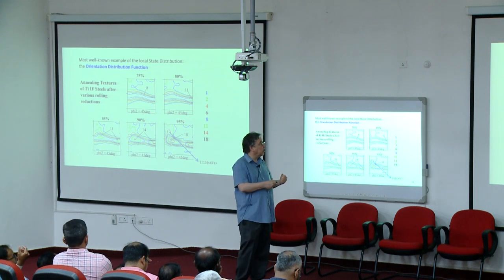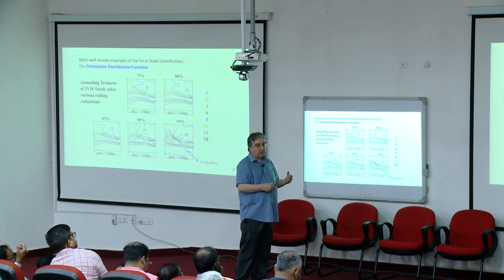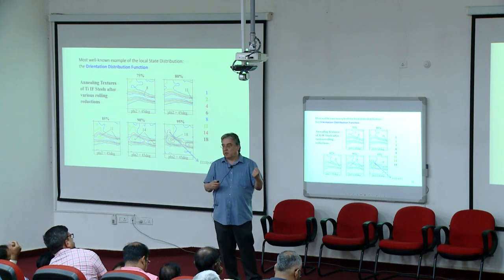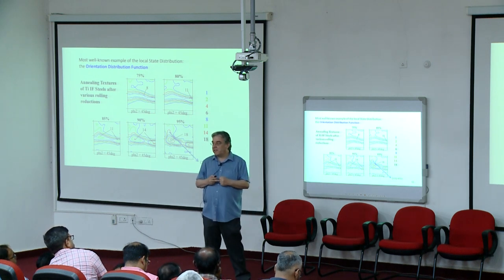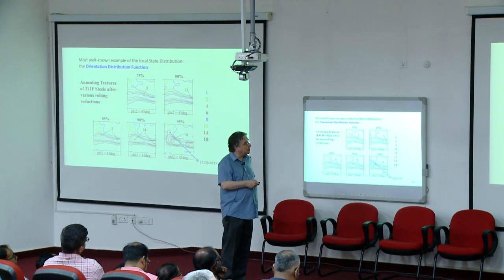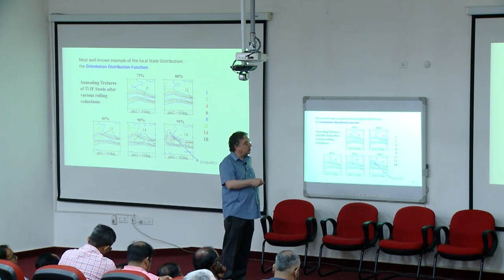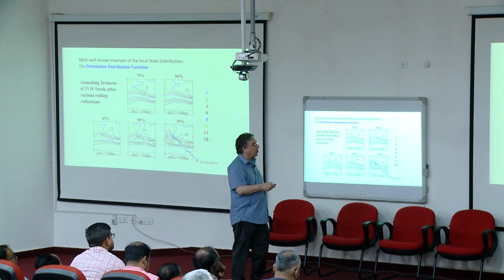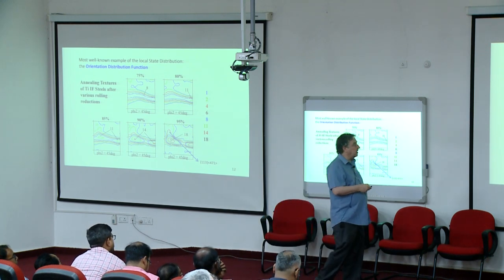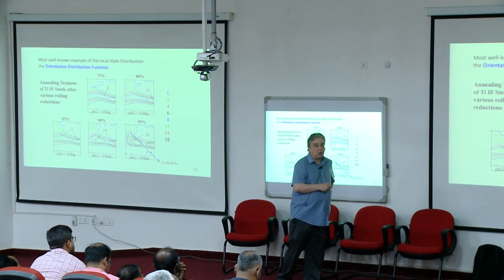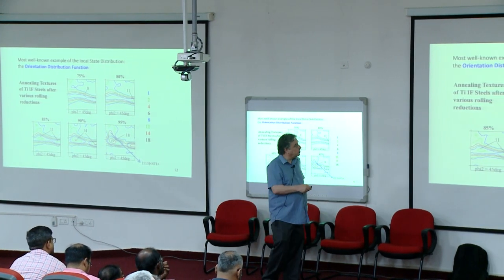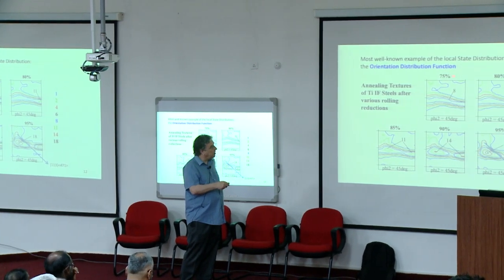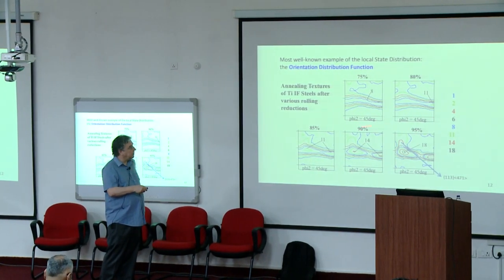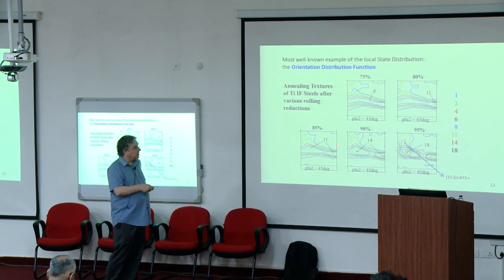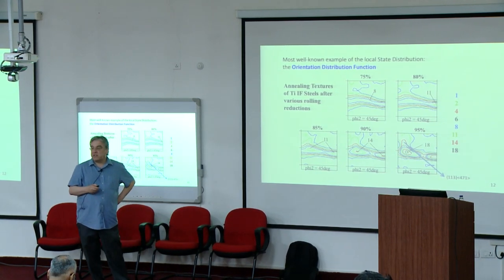And here, for example, these are annealing textures of a simple titanium IF steel. This is much simpler than the dual phase steel. This is a single phase ferrite material. And you can see this is the typical texture that you observe after rolling 75% of steel and annealing. It has what we call gamma fiber texture. But if you change the rolling reduction from 75 to 80, 85, 90, 95%, you can see that these textures change, these distribution functions, because that's what they actually are, they change.